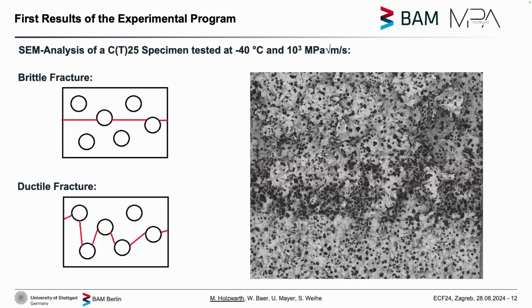And here at the brittle fracture, the crack just goes through the material, through the matrix, and just opens up those graphite particles which are in its way. While for the ductile fracture, the crack goes the path of lowest energy and goes from particle to particle, resulting in this very populated space because every single graphite particle is visible. That's the current theory. As I said, we are still working on more tests. With more tests, we can validate it or change it.